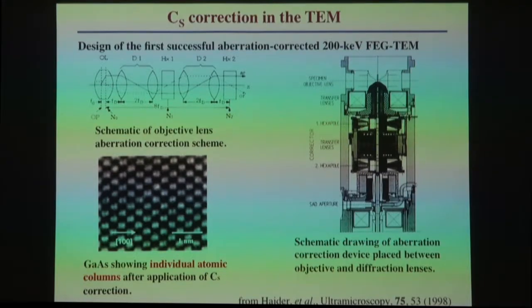Okay, enough of the offline or software approaches. Let's look at the hardware approaches. So CS correction in the TEM, very simple construction. In fact, here is your objective lens. There are two transfer lenses, quite weak lenses, a hexapole, two more transfer lenses, and another hexapole. It's quite easy to build this system with two transfer lenses, hexapole, two transfer lenses, hexapole, and put it inside a regular microscope, in this case a CM200.